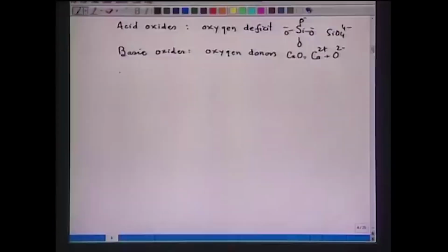So, now, if we want to reduce the viscosity of acidic oxides, that is only possible when we break all the 4 vertices of the tetrahedra. Then the size of the ion will be smaller, the energy required for flow will be smaller, and the fluidity of the slag will be very high. Considering that the most important oxides in steel making are SiO2 and Al2O3, Al2O3 also behaves in a similar way.